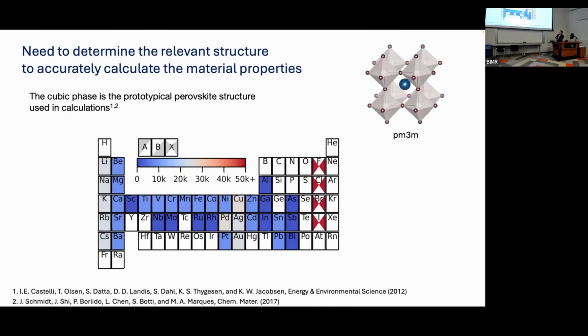From a computational perspective, if you want to screen this large space, so actually calculate the properties of all these 200,000 materials, where do you start? You start from some structure that's been recorded by the experimentalists. We download the CIF file, and then you could take all the elements and substitute them on the lattice. That combination of different elements will change the stability. It will also change the band gap. This strategy of using some template and then combining many, many different elements has been adopted before, and that allows you to screen these very, very large spaces.